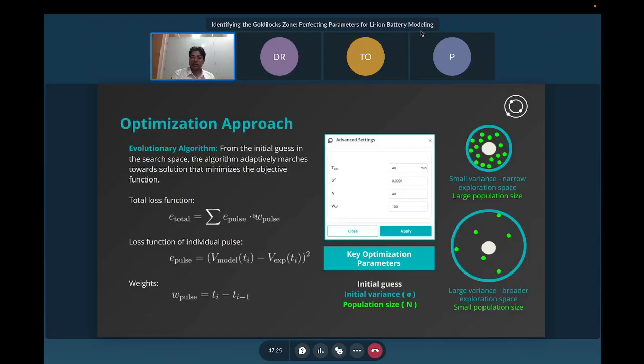And then we start weighing it because there are different portions of these pulses which are important in different senses. Like I mentioned earlier, the lumped internal resistance of the cell and the reaction rates are important in deciding the initial voltage drop. And then there are the diffusion constant and reaction rates which decide the slower decay of the voltage. And thus these errors need to be weighed appropriately so that we give equal weightage to the important aspects of these parameters. And once we have all these errors summed for a particular SOC, we minimize this error by subjecting it to the optimization algorithm. And we repeat this optimization process for the set of pulses at different SOCs. So what happens is that in this process, we obtain the parameters at different SOCs by doing the optimizations on each of these individual pulses.